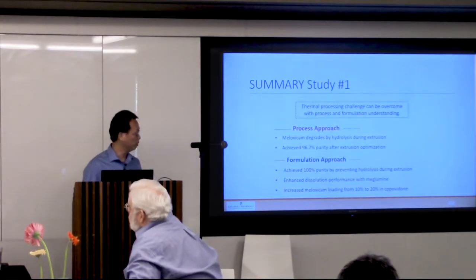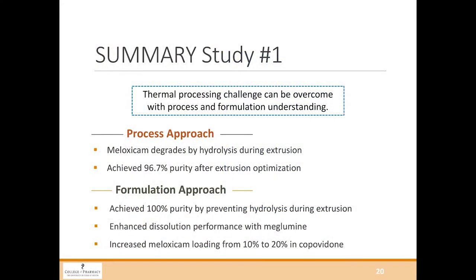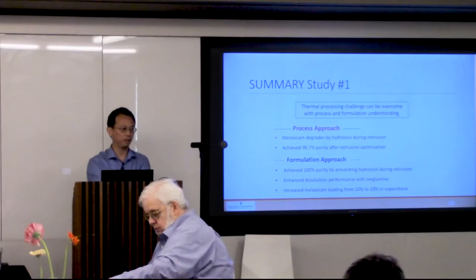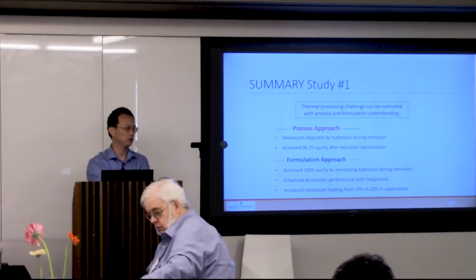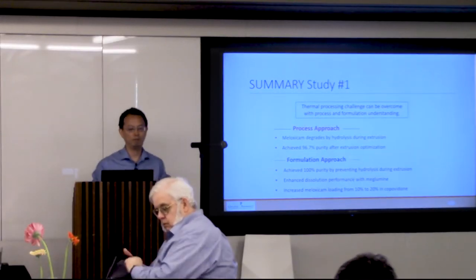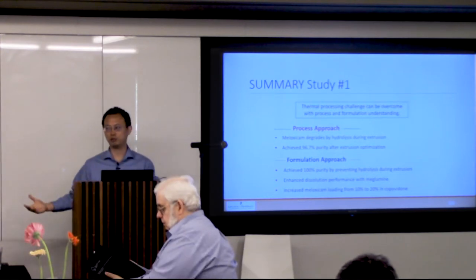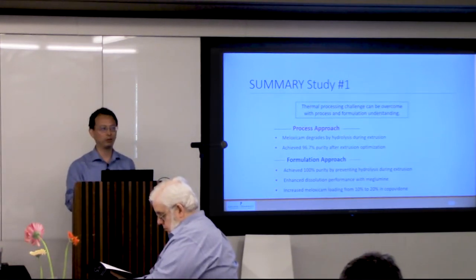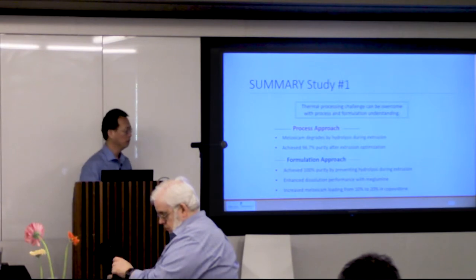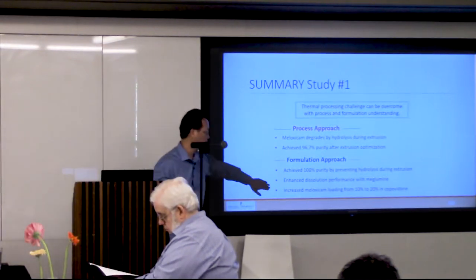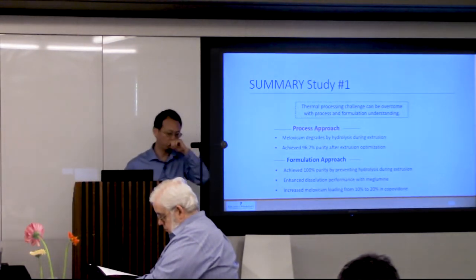So here's the summary of study number one. This compound degrades by hydrolysis, and the best we could do by process was 97% purity. But with this in situ interaction mechanism, we're able to minimize degradation, actually totally got rid of degradation. Process only carried us so far. By this in situ reaction, we got rid of the degradation. And also we can increase the loading of the drug.